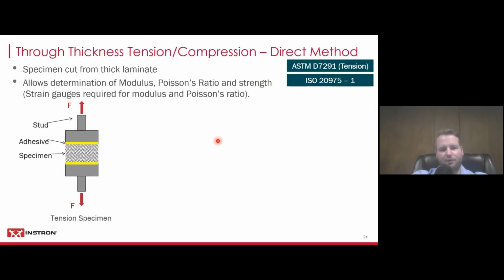Then there is the through thickness direction. So through thickness, tension, and compression. And there are different methods. This is the direct method, and ASTM D7291 covers this, or ISO 20975. The specimens are typically cut from very thick laminates, and it allows you the determination of the modulus, Poisson's ratio, and the strength. But you do require, again, strain gauges. Like for many composites tests, strain gauges are required to determine the modulus and the Poisson's ratio.